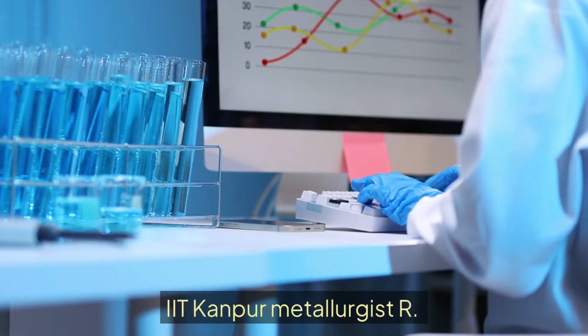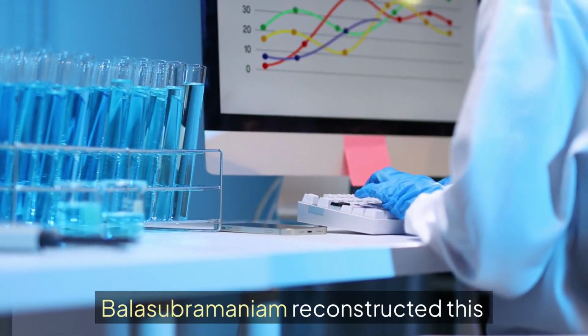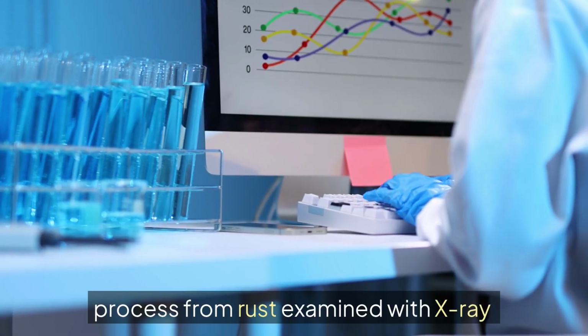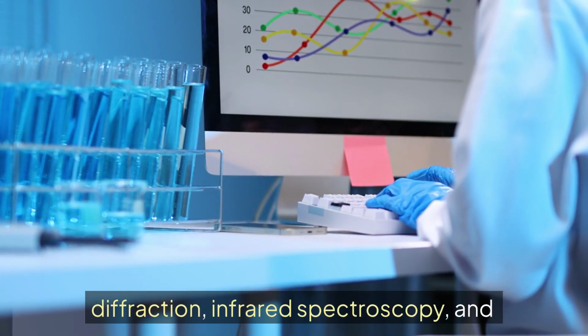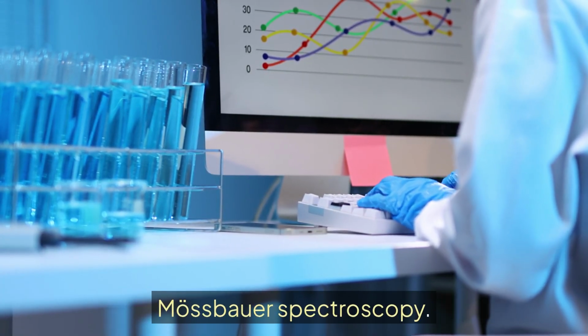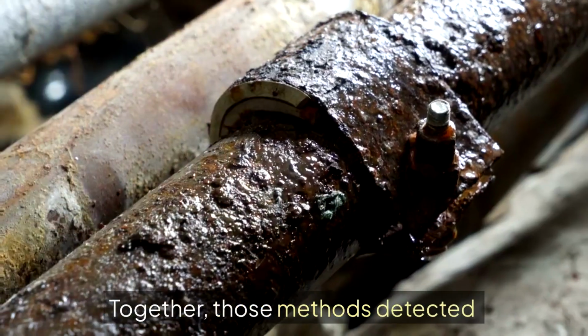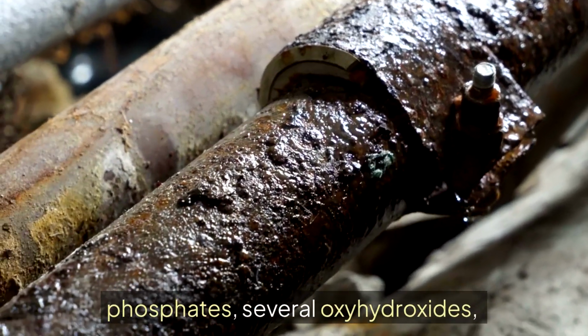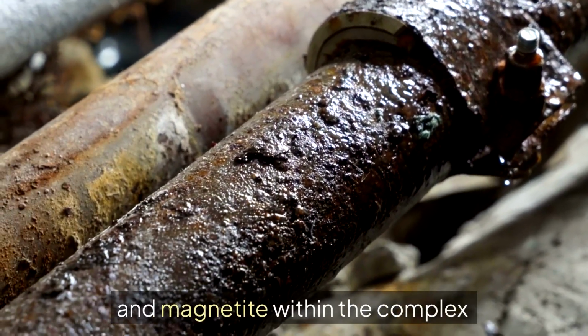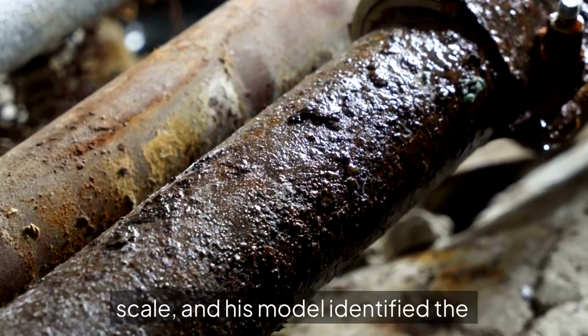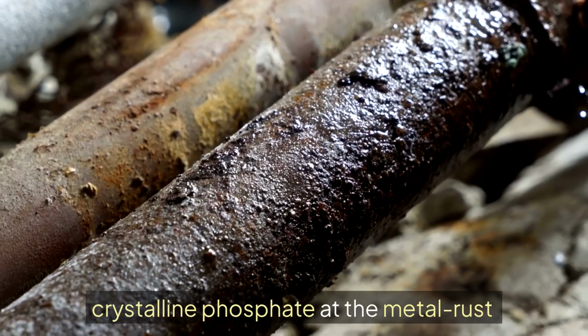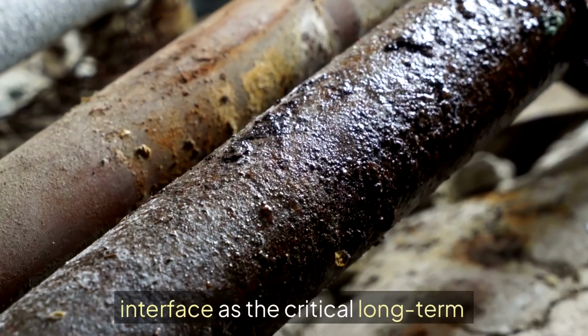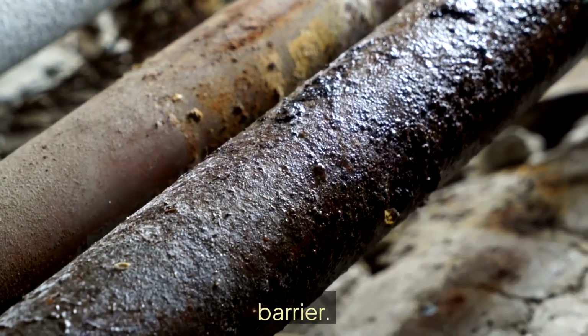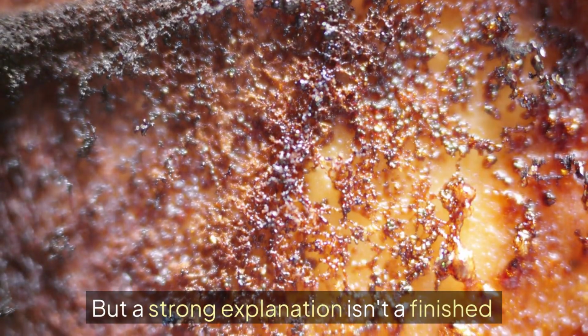IIT Kanpur metallurgist R. Balasubramaniam reconstructed this process from rust examined with X-ray diffraction, infrared spectroscopy, and Mössbauer spectroscopy. Together, those methods detected phosphates, several oxyhydroxides, and magnetite within the complex scale, and his model identified the crystalline phosphate at the metal-rust interface as the critical long-term barrier. But a strong explanation isn't a finished mystery.